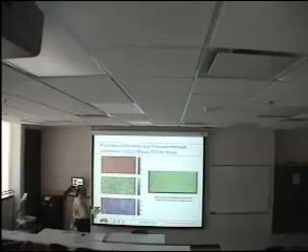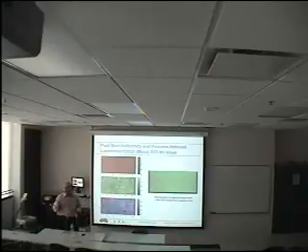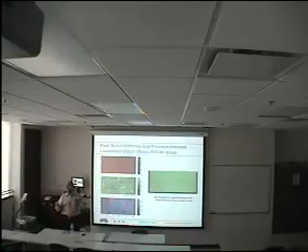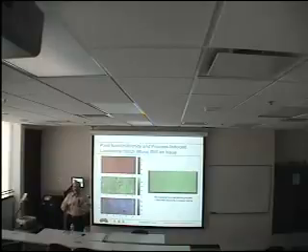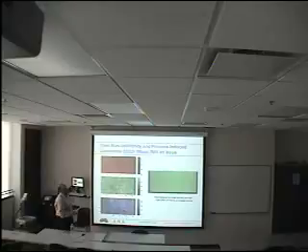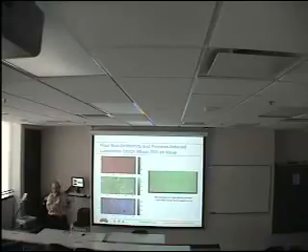But the variation between the bright pixels and the dark pixels here is really only about 7%. Normally, your eye would not be able to pick that up. But because there is a pattern to this, that is, it repeats with a regular structure, the eye is very, very sensitive to patterns, and you can pick that up, even though you might not detect the difference in 2 large areas of 7% difference intensity. And what it turns out is the problem with this is one of the nozzles was clogged. Not completely clogged, just a little bit clogged, so it wasn't putting the same amount of material out with each spit.